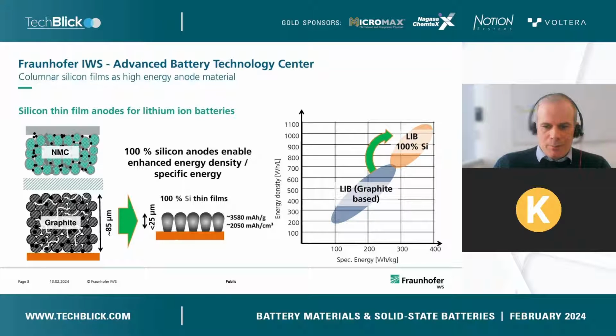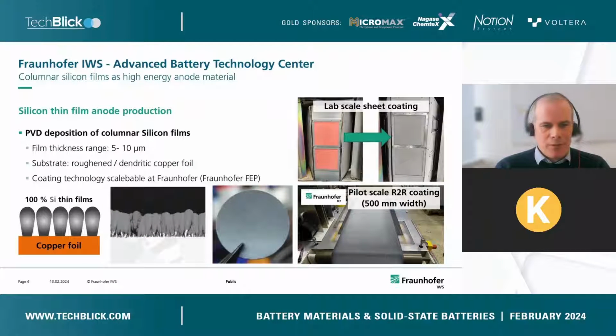We use a quite simple approach based on physical vapor deposition. This is a vacuum deposition technique where we grow the silicon on roughened or dendritic copper foils. And due to the rough surface of the copper, we obtain columnar silicon structures, as you see in the SEM image on the bottom. And this can be done on a small scale in our laboratories, but it also has been demonstrated to be scalable to roll-to-roll equipment on 500 millimeter widths together with our partners from Fraunhofer FEP.